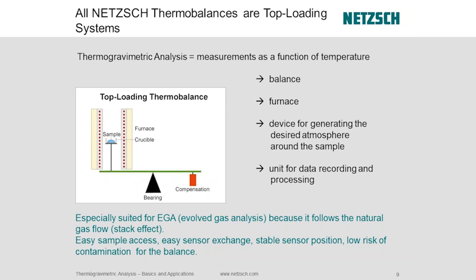If you've got an older style hang down wire type TGA, your balance sits on top normally. And some of you may have had issues with contaminants making their way up. Even though you try to run a horizontal purge gas, those systems usually have a horizontal purge, the off gases tend to want to sneak up and get into that balance and cause havoc with your mechanism. So that's another reason why we really don't advocate that hang down wire type system, because it's just so hard to fight the natural flow of the gas. So with our top loading system, we basically support that, let it go right up and out.